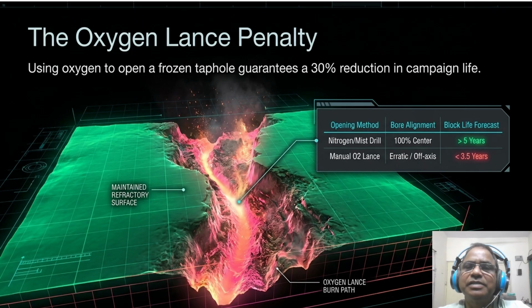The so what is in the block life forecast: using oxygen to open a frozen taphole guarantees a 30% reduction in your campaign life. You drop from a 5-year block life to less than 3.5 years. It's an act of operational vandalism for short-term gain. If you have to use oxygen, you have already failed at hearth management. We must prioritize mechanical opening methods to preserve the refractory surface and the integrity of the hearth.